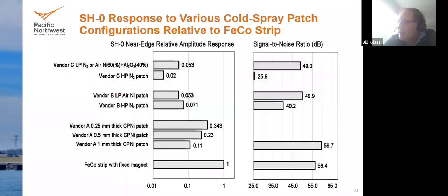This shows the relative amplitudes of things, showing that it does make a difference how you do the cold spray, and there were a number of different recipes that we used, but the bottom line was that when we compared the cold spray versus the adhesive patch, we get similar kinds of responses. So we were pleased with that.